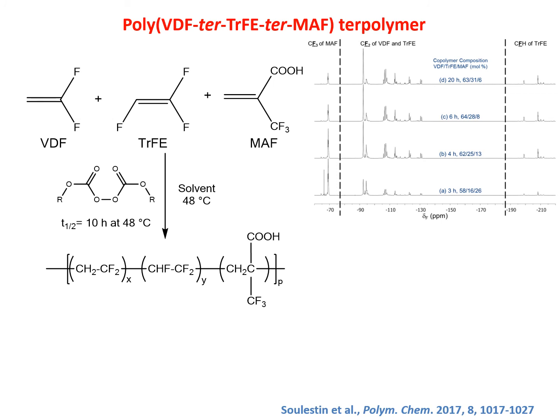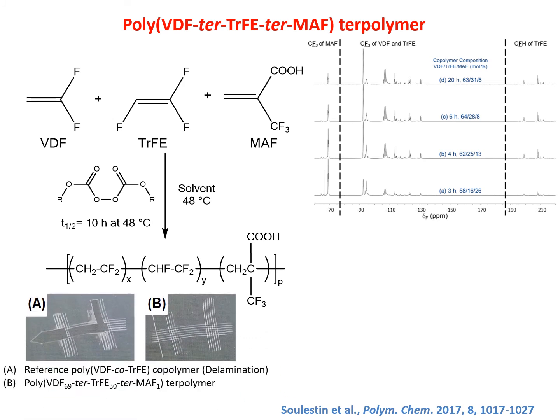I go very fast because probably you're not too familiar. Interestingly, you have a very wide chemical shift range in which you have a CF3 signal assigned to MAF, then a CF2 assigned to VDF and trifluoroethylene, and then the CF characteristic of trifluoroethylene. What is very interesting is that MAF reacts very well with VDF, and when it's totally consumed, VDF is going to react with trifluoroethylene. So the presence of CO2H enables adhesion.